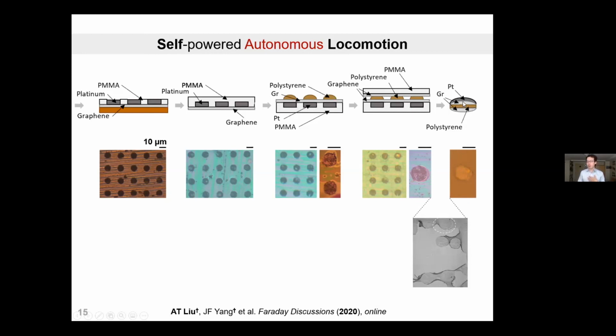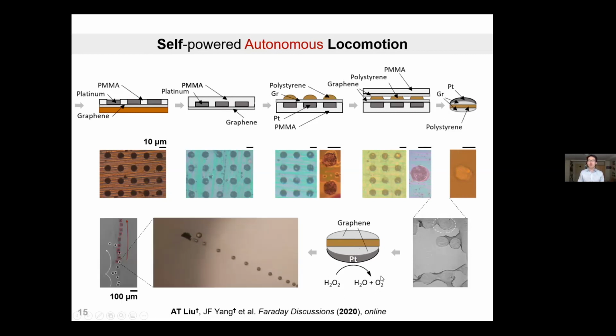original sandwiched structure. So this additional metal layer allows us to do something a little bit unusual, which is that when you put the particles inside of a hydrogen peroxide bath, the platinum can be used as a catalyst to decompose hydrogen peroxide into these oxygen bubbles that allow these particles to generate bubbles and propel themselves to move. So this is just a step in the active locomotion direction, in which, again, we're borrowing knowledge from the colloidal science community, and we're introducing it onto our colloidal electronic devices to make them perhaps a little bit more useful than they are